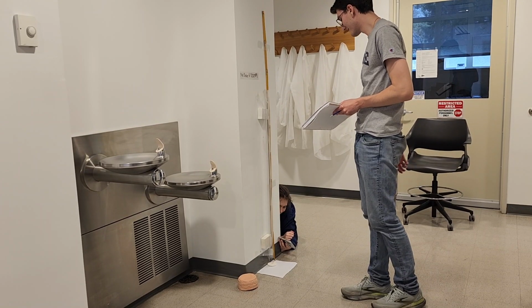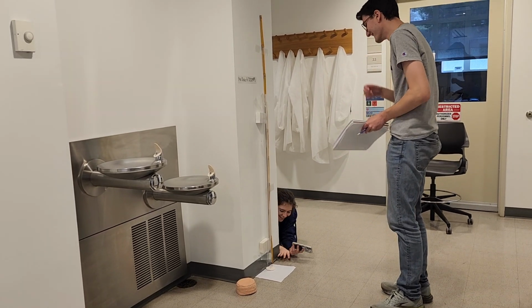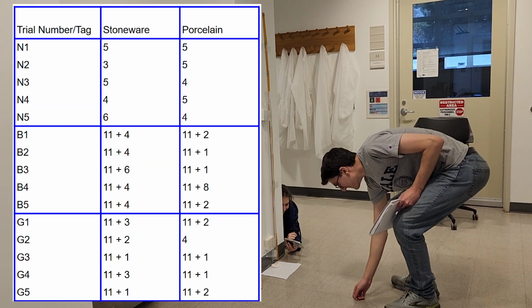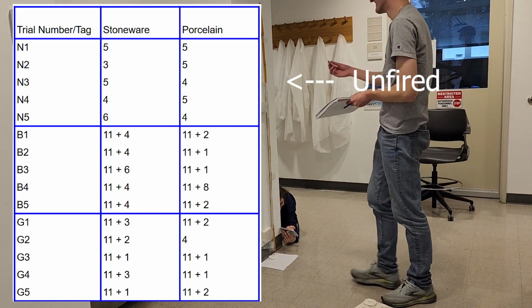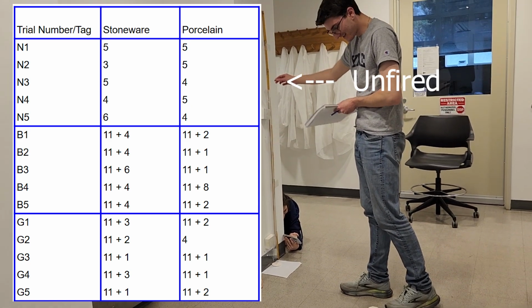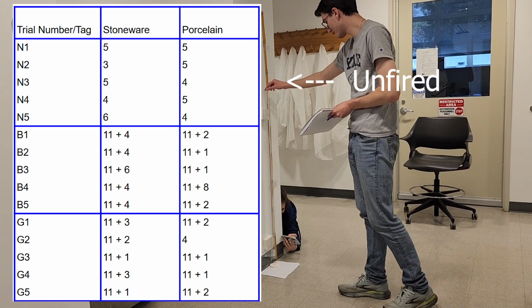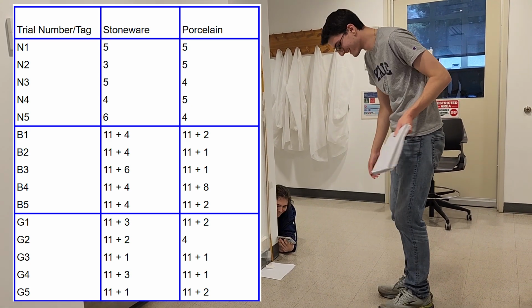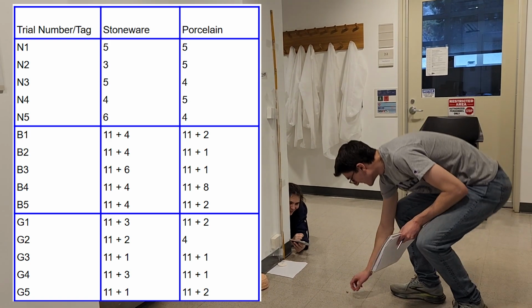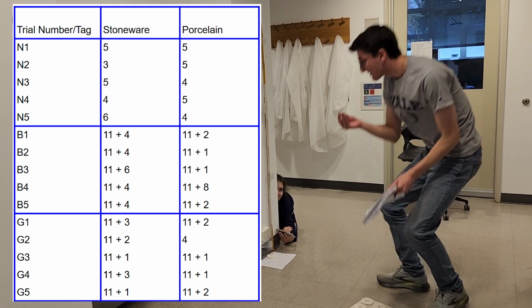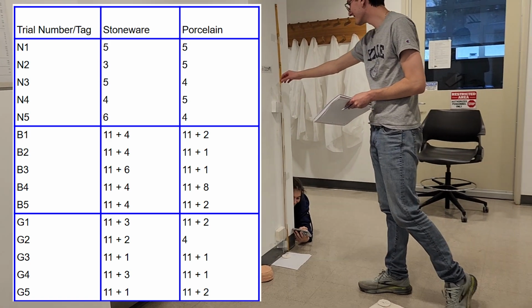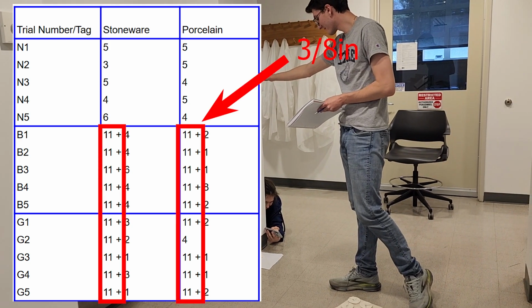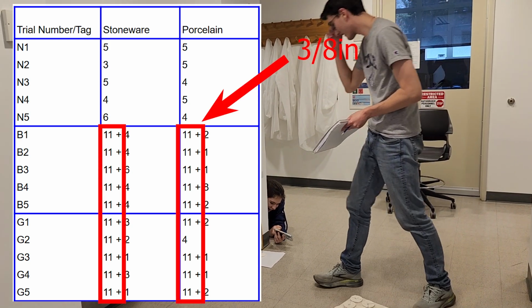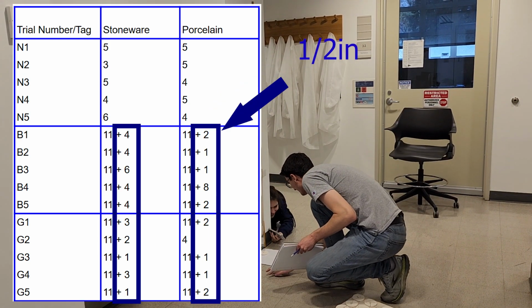After reviewing our drop results, we found that there was a happy medium for firing temperature and durability. The unfired clays broke the quickest, taking on average 4.6 drops with a 3/8 inch ball bearing to break for both the stoneware and the porcelain. The fired ceramics needed a few more drops to break, and we needed to up the size of the ball bearing. Except for one outlier, 11 drops ended up being a reasonable threshold to set before moving up to the larger, 1/2 inch ball bearing.